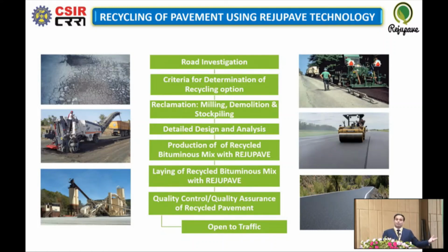Parallelly, the RejuPave rejuvenator also acts as a warm mix additive. The conventional bituminous mix is required to be produced between 150 to 160 degrees centigrade, and we have to lay it between 120 to 130 degrees centigrade in order to achieve the requisite field density. But with the help of it, you can reduce the production temperature by 10 to 15 degrees centigrade. You can produce the mix at 130 to 140 degrees centigrade, and you can easily compact between 100 to 115 degrees centigrade.